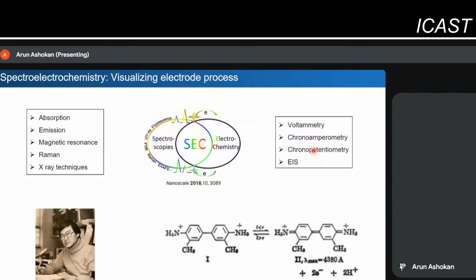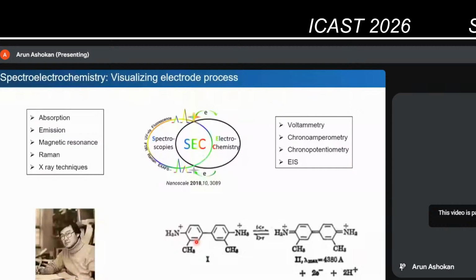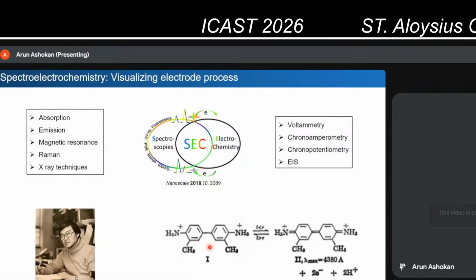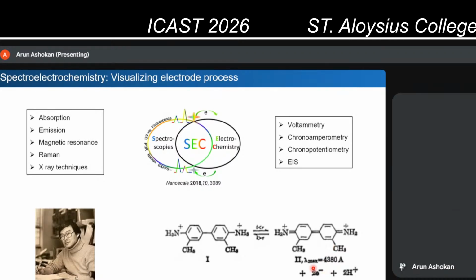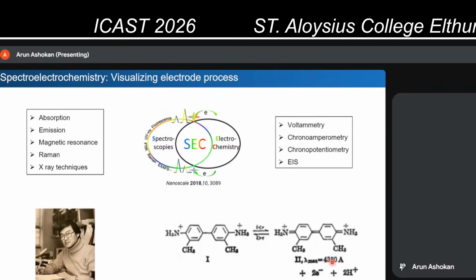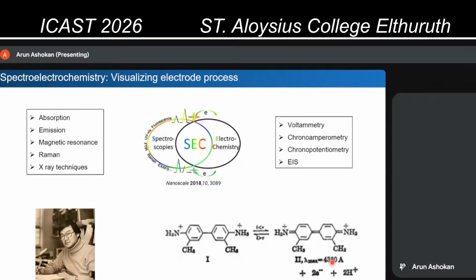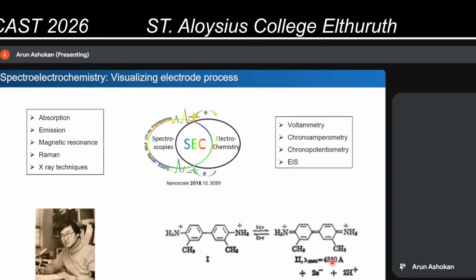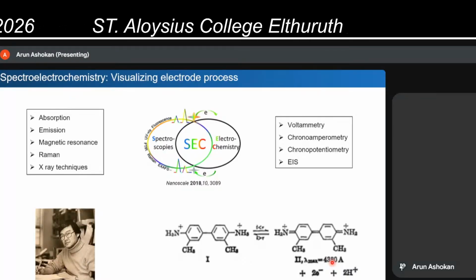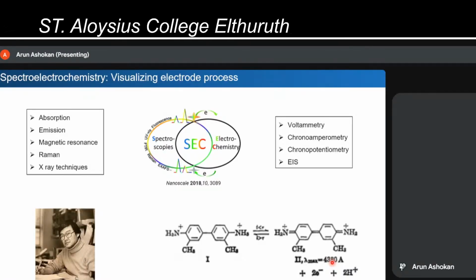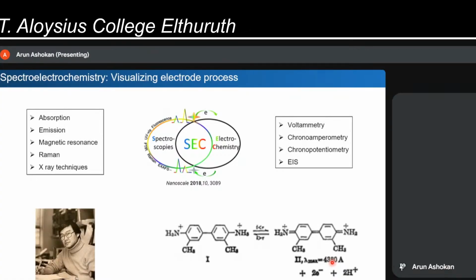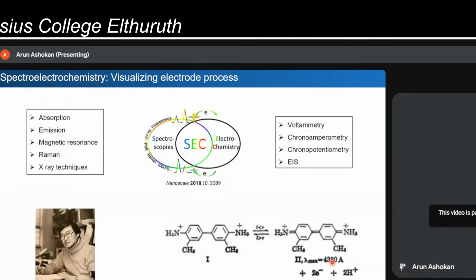Professor Theodor Kuwana was the pioneer in this field. He came up with the first experiment where he oxidized this molecule, called tolidine, to its oxidized form, and simultaneously observed its evolution in the absorption spectrum. So basically, I'll be doing spectroelectrochemistry on these plasmonic semiconductor nanocrystals, and this is how I do the experiment.